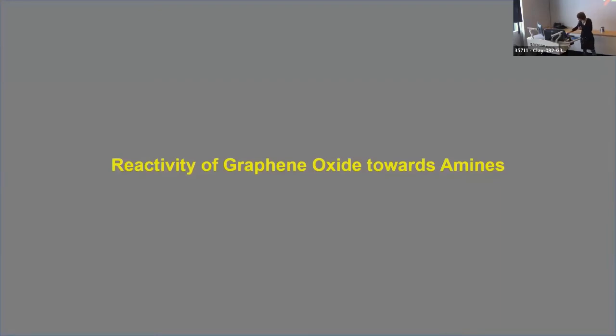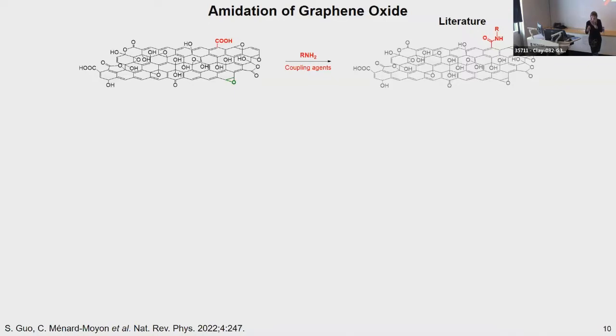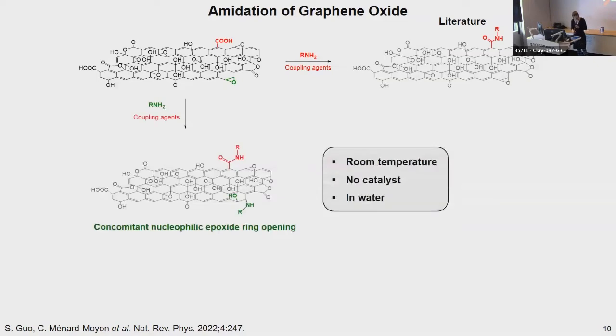So in the literature, the main reaction which is used to functionalize graphene oxide is the amidation reaction. This reaction takes place between the carboxylic acids on graphene oxide and an amine derivative in the presence of coupling agents. Coupling agents are necessary to activate the carboxylic acids, giving the formation of this amide bond. But in fact, in the presence of an amine, the main reaction occurring is the epoxide ring opening.